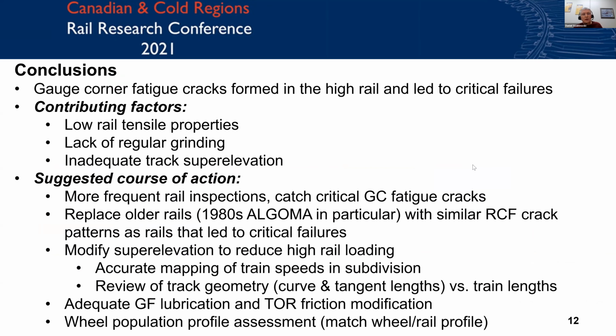So in conclusion, we looked at the gauge corner fatigue cracks formed in the high rail that led to the critical failures. Some of the contributing factors that we saw was the low rail tensile properties. So not the low rail as in the position, but just the low tensile properties here. And those are especially the yield and the UTS, which might cause some of the plastic flow to be more prominent in this specific type of rail.